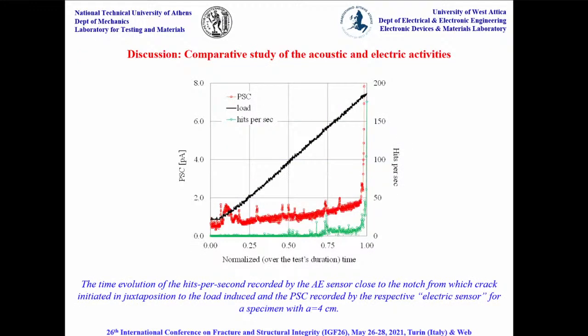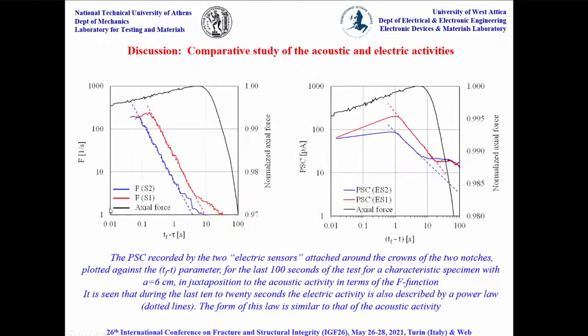Then we focus our attention on the electric signals. You can see here the electric current recorded, the hits per second and the load. Again, you can see that what happens is mainly during the very last seconds. So again, we focus attention on this inverse time arrow. And you can see here the acoustic activity, here described in terms of their function, just to emphasize that it does not play a crucial role whether we describe the acoustic activity in one or another parameter.